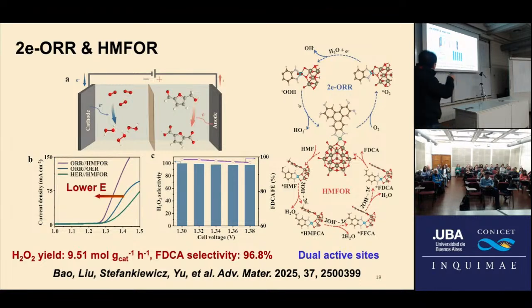I'm not going into details, but here you can see the overall voltage can be decreased, compared with either the OER or the HER. So we can do this at a low voltage. And here you can see the hydrogen peroxide yield can be increased further, and the FDCA selectivity is also very high. The mechanism is also demonstrated.